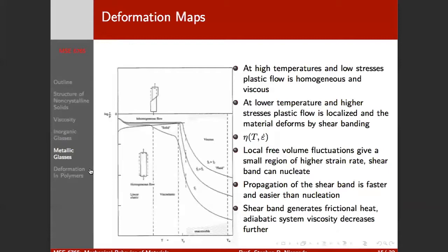So all of our strain becomes localized to some region. And we have a shear band that, basically on yielding, propagates immediately across our sample. And once we have a shear band that's all the way across our sample, the whole thing comes apart, right?